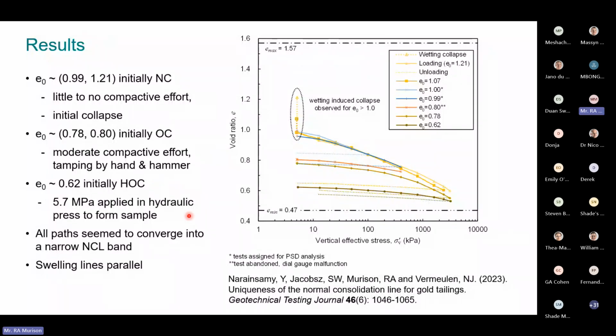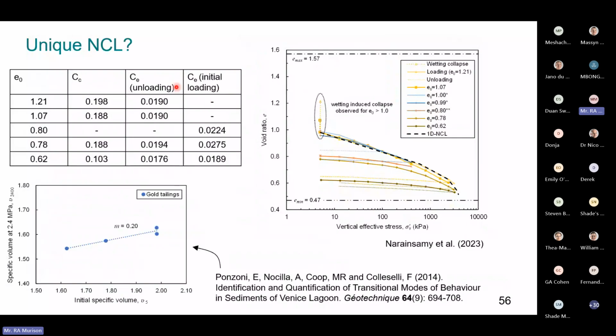And with all these results, they seem to converge into a narrow, normally consolidated line band. All of the swelling lines also seem to be parallel, so our unloading lines and our initial loading lines for the overconsolidated samples are also parallel for practical purposes. If we look at this in a bit more detail, we've got our expansion index during unloading and during the initial loading of our overconsolidated samples. These numbers are quite similar. And then the compression index of our samples other than the 0.6 sample were all very similar as well.